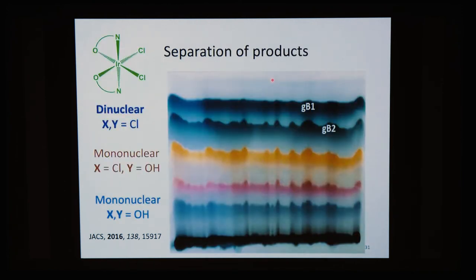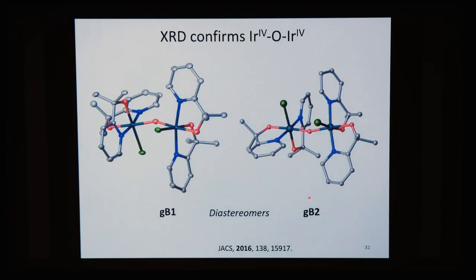So now we can separate the products again. And GB1 means the green isomer converted to the blue bridging oxo, one being the fast moving isomer on the plate, and GB2 the slow moving isomer. And then we've also identified the other ones, but I won't go into those. And the XRD confirms the iridium oxygen iridium. These are diastereomers, so no big difference between them. We have retained the green configuration with all of the anions in the same plane.